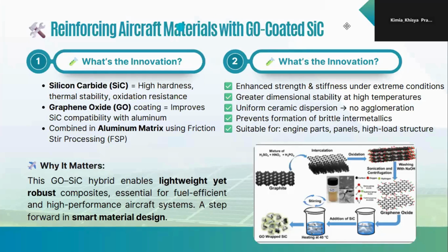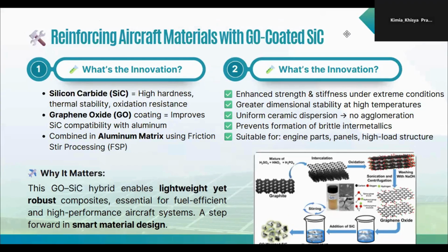Next is reinforcing aircraft material with graphene oxide and silicon carbide aluminum. What's the innovation? First, silicon carbide has high hardness, thermal stability, and oxidation resistance, while the graphene oxide coating improves silicon carbide compatibility with aluminum. Combined in an aluminum matrix using friction stir processing is the process.